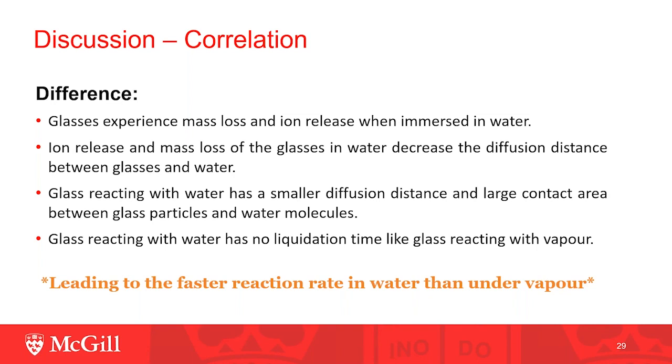This is because there is weight loss and ion release when immersing in the water. This ion release and weight loss of glasses in the water decrease the diffusion distance between glass and water. Glass reaction in the water has a smaller diffusion distance and a larger contact area and no liquidation time like vapor-induced reaction. This results in a faster dissolution rate than the vapor sorption reaction rate.